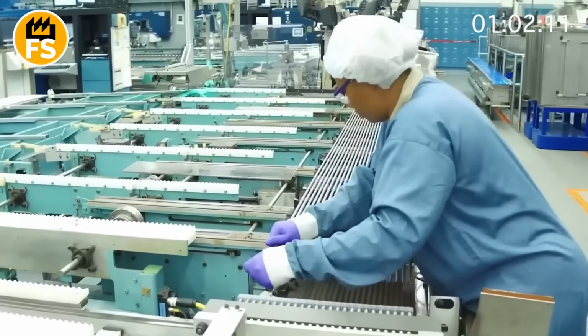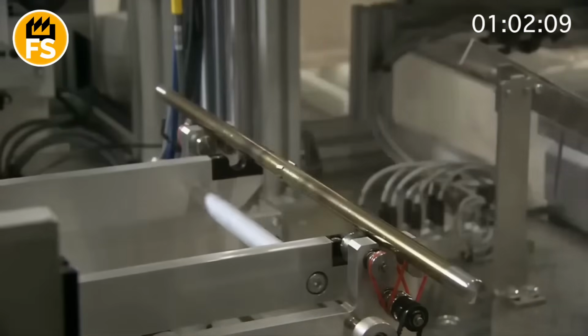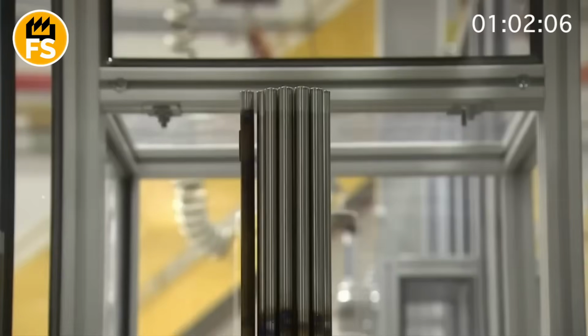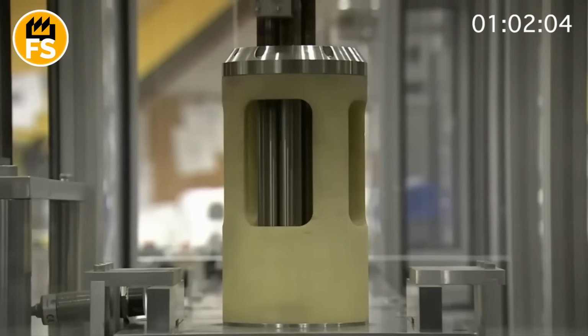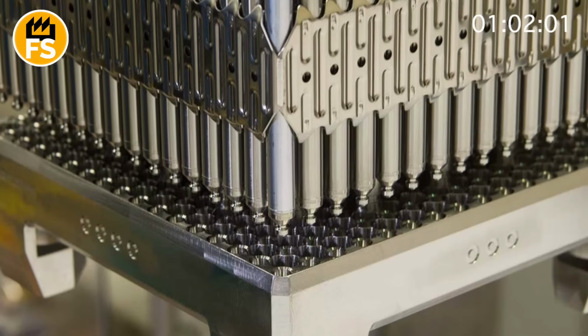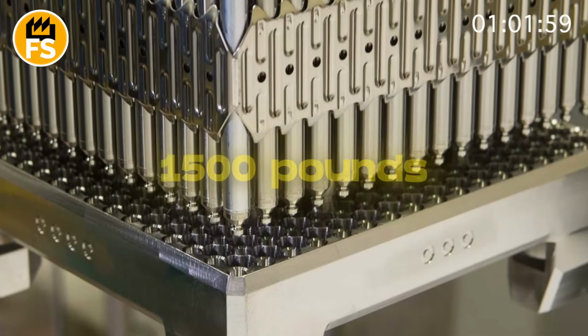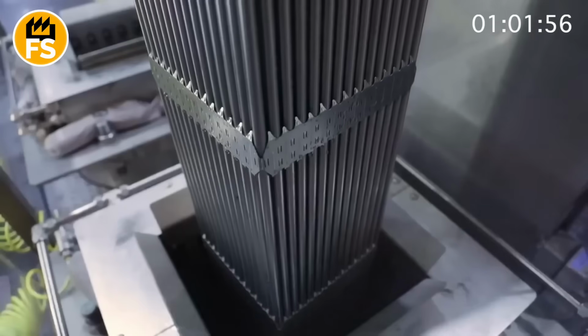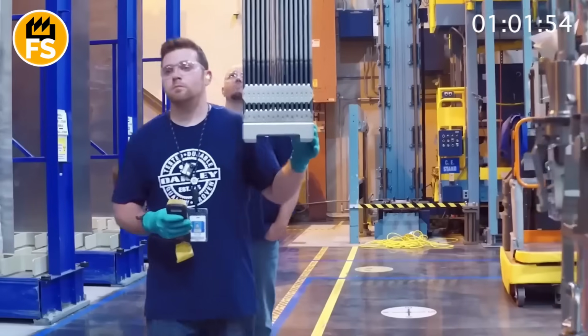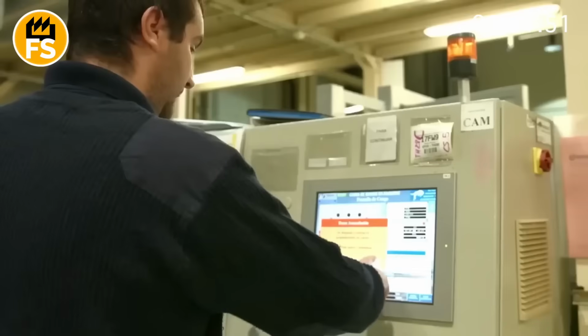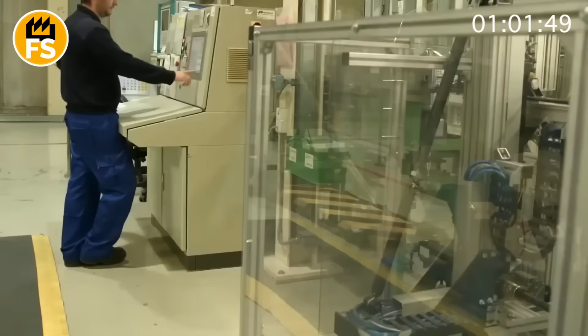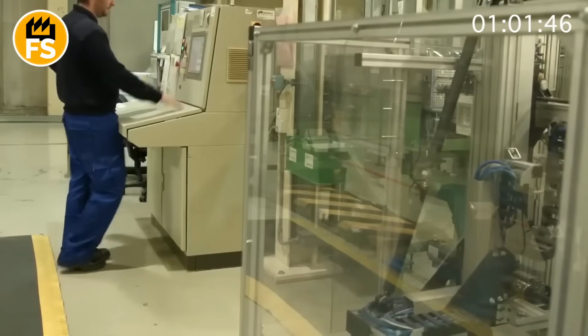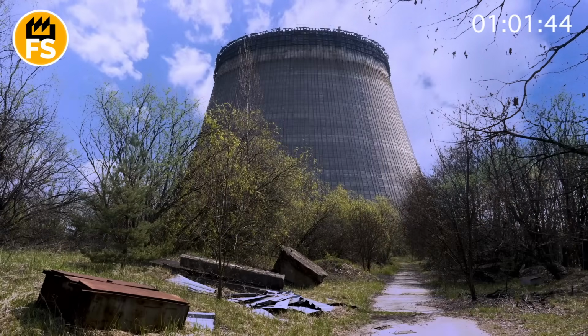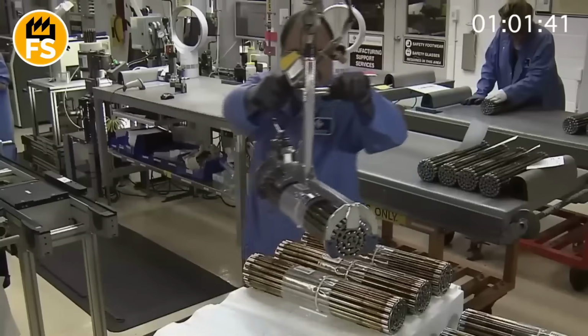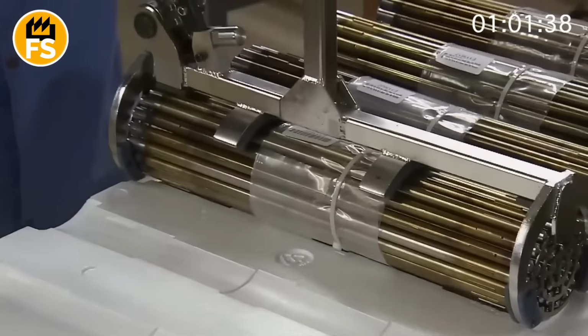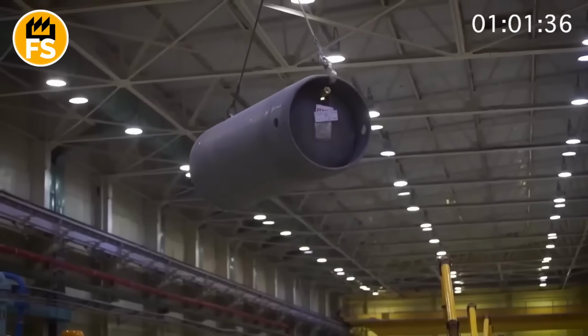The rods are hermetically welded and combined into modules, fuel assemblies. They look like a frame of several dozen tubes, assembled in a square. One such assembly can weigh over 1,500 pounds and works for up to 6 years in a reactor. After assembly, testing for leaks, uniformity of filling, weld integrity, behavior under temperature. There are no trifles, because each of them can cost not just money, but lives. The finished fuel is packed in armored containers that can withstand impacts, fire, and falls from a height.